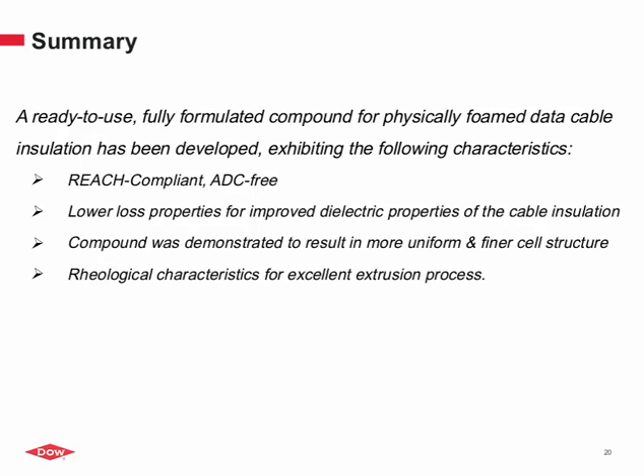So in summary, what we have developed is a ready-to-use, fully formulated compound for physically foamed data cable insulation, exhibiting the following characteristics. Number one, this is an azo-free system. It exhibits lower loss properties compared to the conventional control. We have also demonstrated that we generate a more uniform and finer cell structure, which is necessary for these thin wall constructions. And of course, it should have better compressive strength compared to a system which would produce a larger cell size. And rheological characteristics are important. We could not have achieved that if we did not have the proper rheological properties.